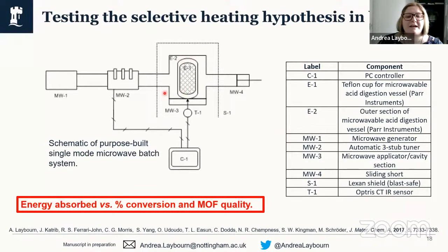So we housed a solvothermal vessel in there, and looked at how we would deliver the microwave energy and the impact of that. We were particularly interested in different ways of delivering the energy, which requires us to be able to measure the energy absorbed by the reaction mixture. So we looked at low microwave power for a long period of time, and then changed that to a high microwave power for a very short period of time, delivering the same amount of energy, just in different ways. And then we looked at the effect on the percentage conversion, so in our case, the yield of the MOFs we were producing, and the quality of the MOF material, which in our particular case we wanted to be highly crystalline and highly porous.